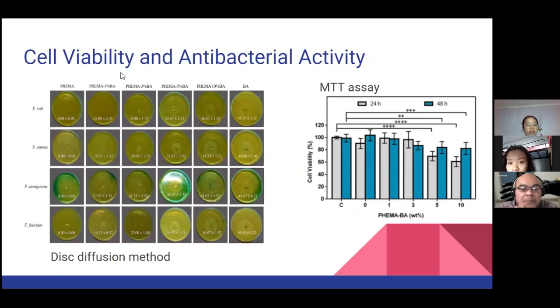This is important. Why? Because this is whether it is biocompatible or not to our eyes. And for the antibacterial, it is also an important parameter, because there shouldn't be any bacteria growing in or surrounding our eyes, because it could cause infection. This is the antibacterial activity, which is tested by this diffusion method with different types of bacteria. As we can see, I think it's not that clear, but we can see the circle here. The diameter is getting bigger, because at the middle here is the hydrogel, and if the diameter is getting bigger, it is caused by the boric acid in the hydrogel that could kill this bacteria.